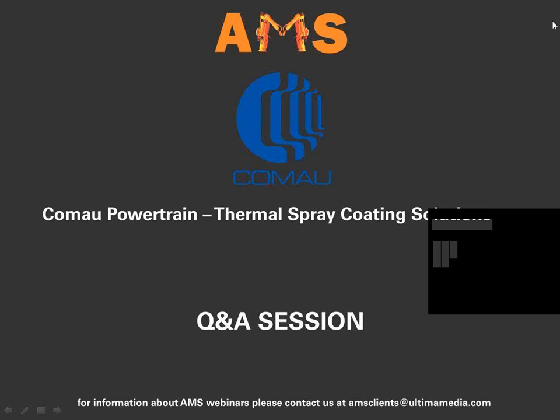Once you start dealing in film technology or coatings in the 100 micron range, the impact of the thermodynamics is really reduced. So at that point, trying to focus on using an aluminum provides no benefit. There is the ability to use cored wires. Such testing has already been completed, and you can spray some fairly interesting metallic materials, even composite metallic materials. But for the most part, everything that we're doing for production tends to be focused around iron-based alloys, in particular 1010 or stainless.